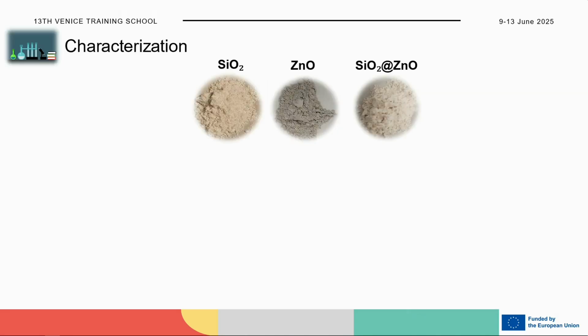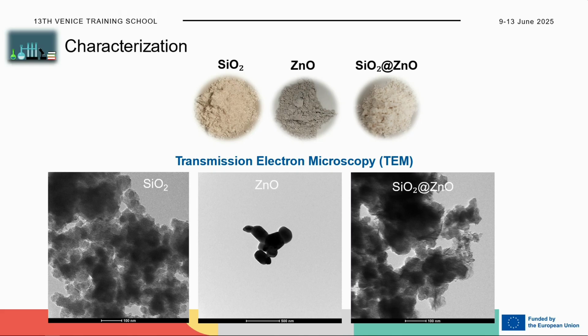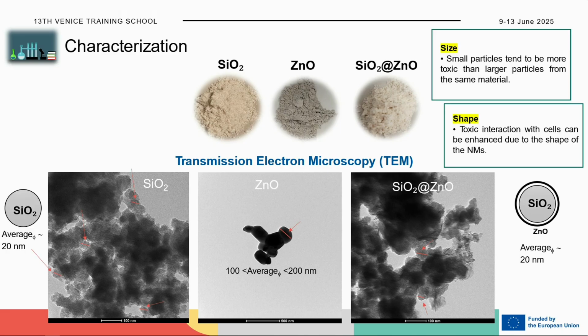So starting from the characterization point of view, as already Eva told you, we started just from the TEM analysis, trying to look at the differences that we can observe between silica dioxide nanoparticles and the advanced material, and we use zinc oxide nanoparticles as reference, as I told you before. And what we observe is that more or less the average diameter by TEM was a little bit similar between the silica dioxide nanoparticles alone and the silica dioxide particle with the zinc oxide layer on top. So in this case, we look at the size and also at the shape by TEM. And as far as the zinc oxide nanoparticle is concerned, we observe a higher particle diameter, between 100 and 200 nanometers. That was our reference material.